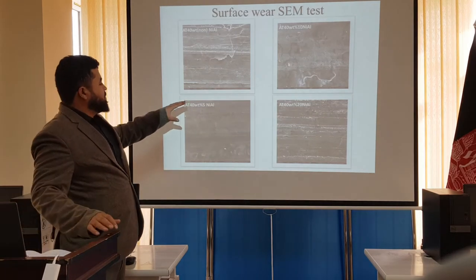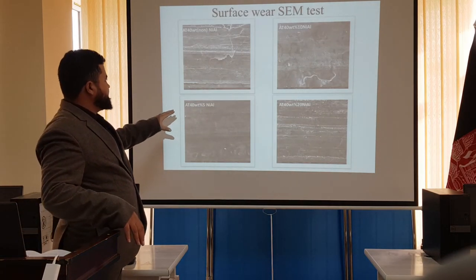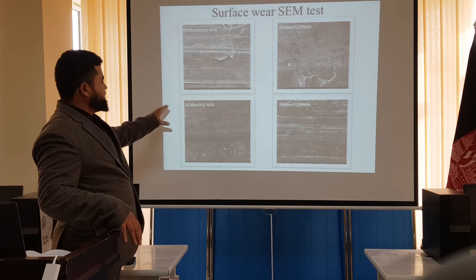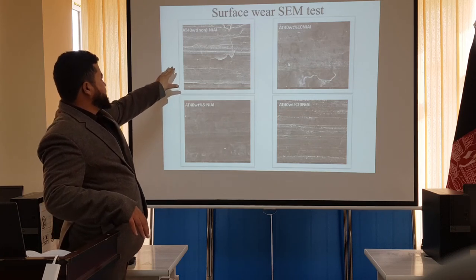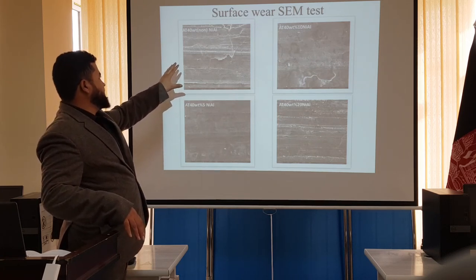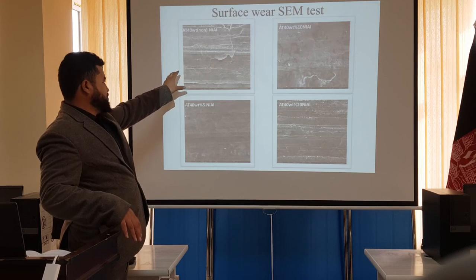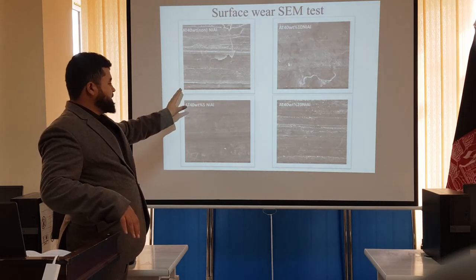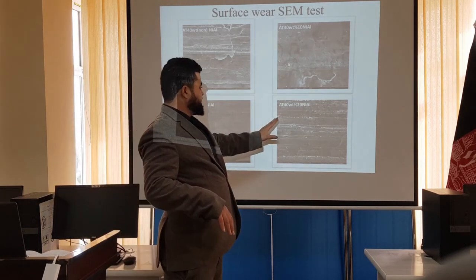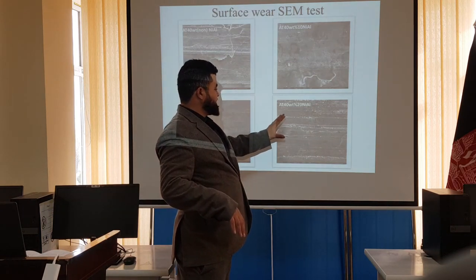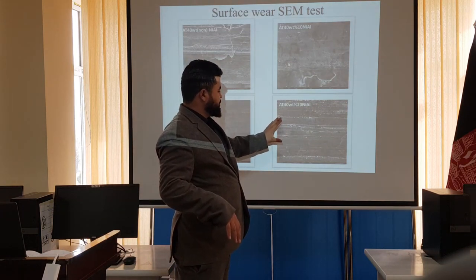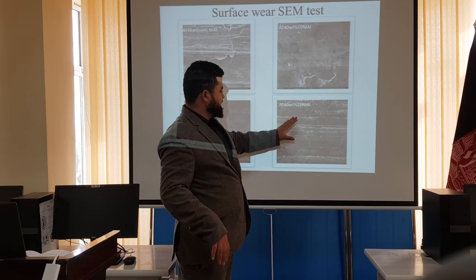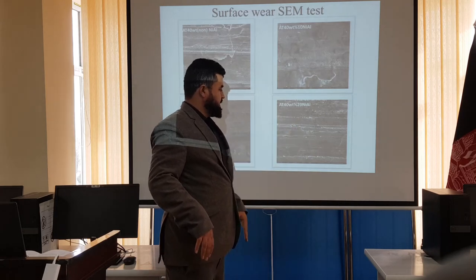We also looked at the wear test. After the wear test, we got this picture. Here, AT40 without nickel aluminum has too many cracks. But here, AT40 with 20% has not too many cracks, and we can see the composition of nickel aluminum, the white area and dark areas in AT40.